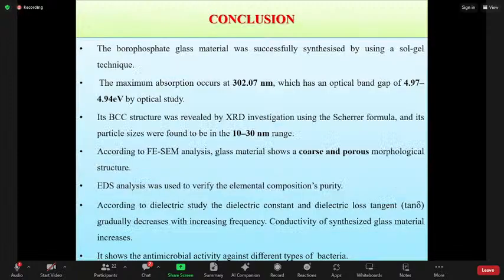Then we see the conclusion. In the conclusion, borophosphate glass material was successfully synthesized by using the sol-gel technique. Then in the UV visible spectrum, maximum absorption occurs at 302.07 nanometer and the optical band gap is 4.97 to 4.94 electron volt. According to XRD, it shows a body-centered cubic crystal structure and the particle size is observed in the 10 to 30 nanometer range. According to FESEM analysis, the glass material shows a porous morphological structure.